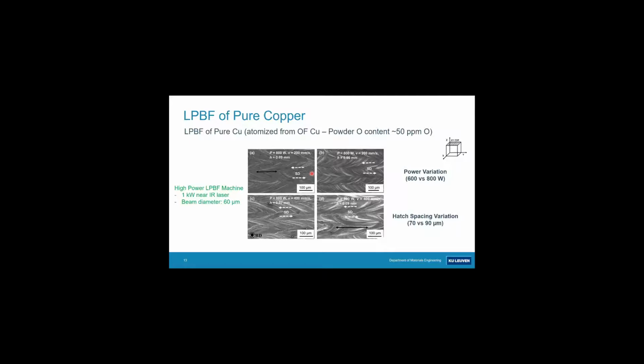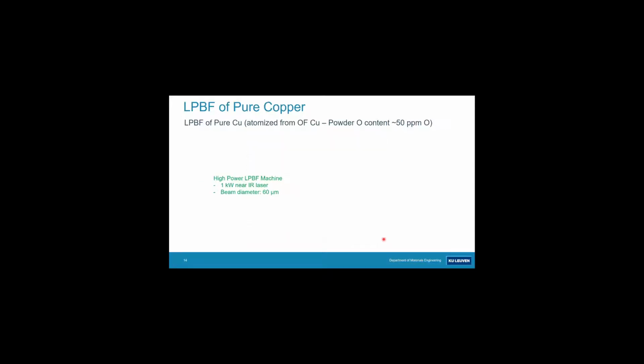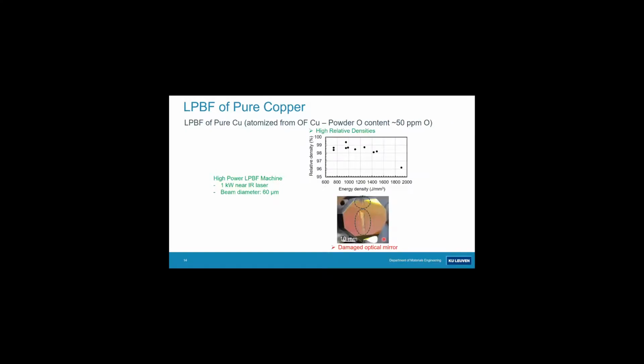We first tried to process pure copper with a very powerful laser, so a 1 kilowatt near infrared laser. This was atomized copper powder from OF copper, and you see that during atomization you pick up some oxygen, so the powder had about 50 ppm of oxygen in the powder state, and then you see the processing conditions here at high laser powers and very low scan speeds. We managed to fully densify pure copper, which was in a way good news. There was also some bad news. So the good news was, okay, we achieved high relative densities.